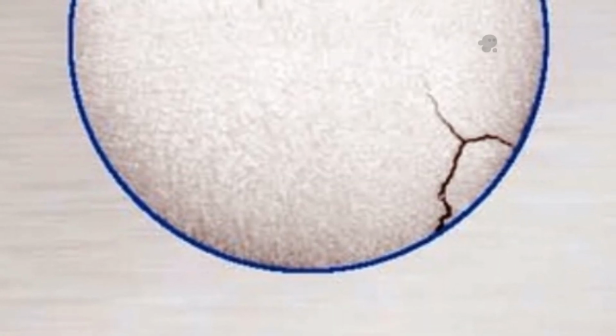Poor quality shot, on the other hand, shatters. It explodes into multiple sharp, angular fragments. This is brittle failure, often caused by improper heat treatment or those internal voids we talked about. This kind of shot will break down almost immediately in your machine, creating massive amounts of dust and doing very little effective work.